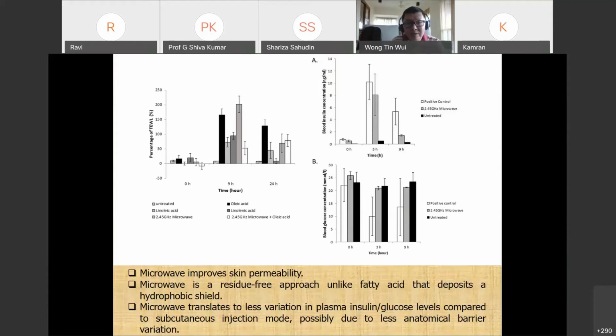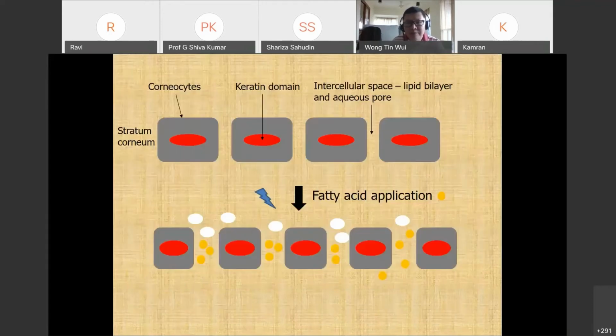This is further illustrated through a transepidermal water loss experiment. In this experiment, treating the skin with microwave is accompanied by a high level of transepidermal water loss. So the microwave can actually improve the skin permeability. And more importantly, microwave, compared to fatty acid, is a residue-free approach, unlike fatty acid, which deposits a hydrophobic shield, which is highly unfavorable for skin transport of insulin.